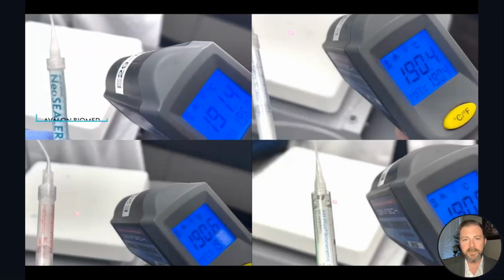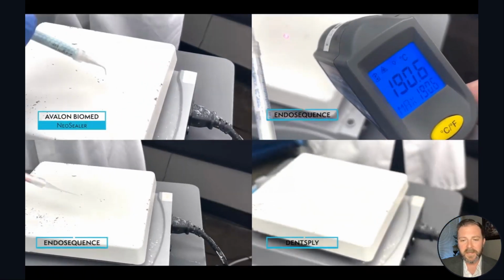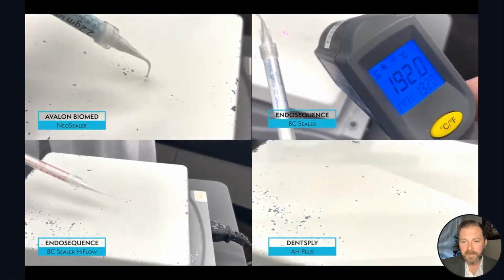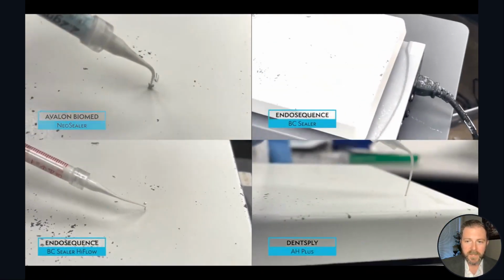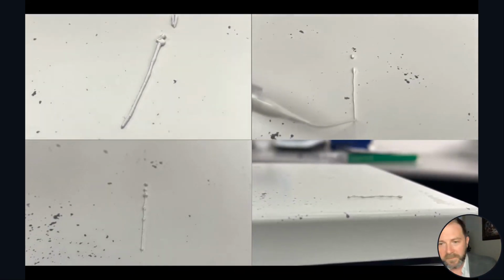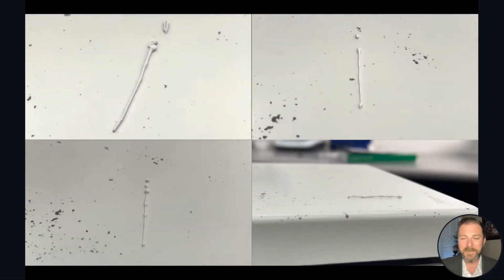So I'll show you that one more time, just so that you can see. Again, watch the bottom right, the Dentsply AH Plus. And the reason why it does this is because of the carrier that it contains, and it contains a lot of carrier relative to the cement content here. And so you just see it kind of pill up and make a little snake.